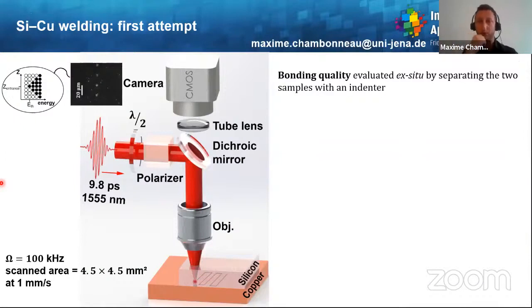To do so, we will use the following setup illustrated here. And we will use silicon and copper for illustrating semiconductor to metal laser welding. Basically, the setup is essentially the same: one laser, one target, and some diagnostics. Concerning the laser, the laser pulses are around 10 picosecond duration at the same wavelength, so 1.55 micron wavelength, for which silicon is highly transparent. Then we classically adjust the input pulse energy by means of a half wave plate and a polarizer before the beam is focused to the interface between silicon and copper by means of an objective lens.